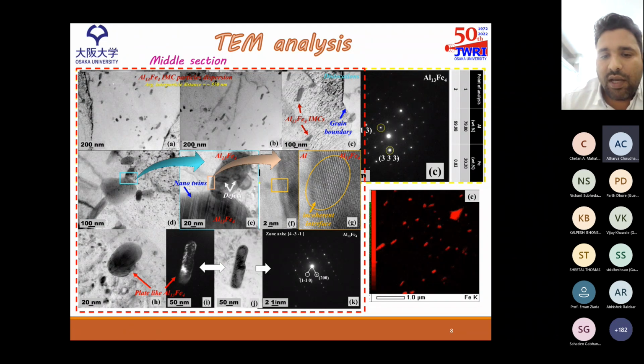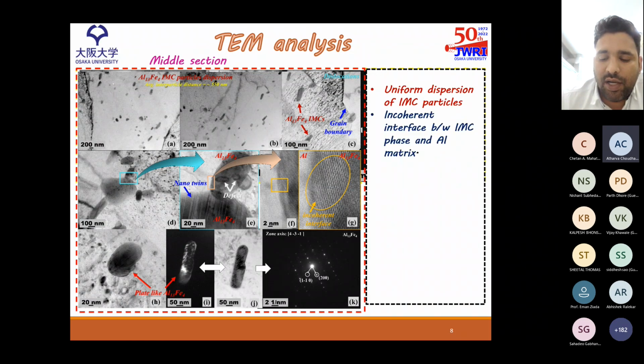Another interesting feature is the incoherent interface, as can be seen here. This is an incoherent interface, so the dislocation movement is further restricted by this incoherent interface, as it has a higher energy. These are the high energy interfaces. So based on these features, we can say that the strengthening is provided in multiple ways by the IMC particles in the aluminum matrix. So here I have discussed the uniform dispersion of IMC particles, the incoherent interface, the nano twins which are formed, and the defect structure on IMC particles.